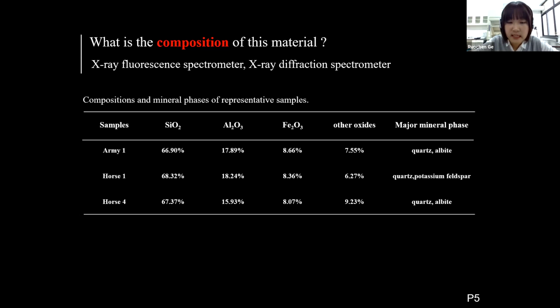Firstly, what is the composition of this material? We used an X-ray fluorescence spectrometer and an X-ray diffraction spectrometer to analyze the powder. The results of some samples are summarized in this table. The samples are mainly composed of silicon dioxide, aluminum oxide, and ferric oxide with other oxides. The major mineral phases are quartz and albite, which are identical with those of potteries.